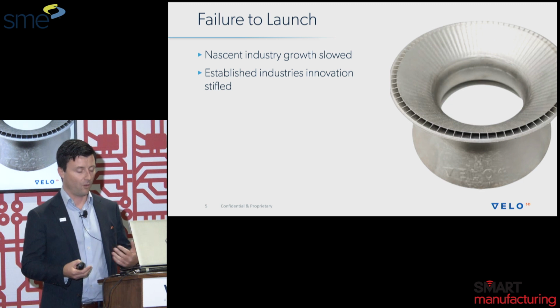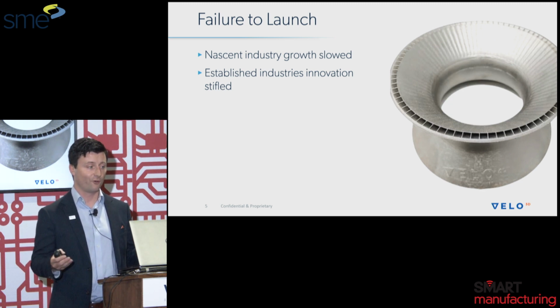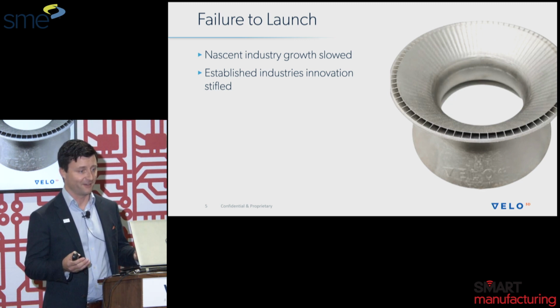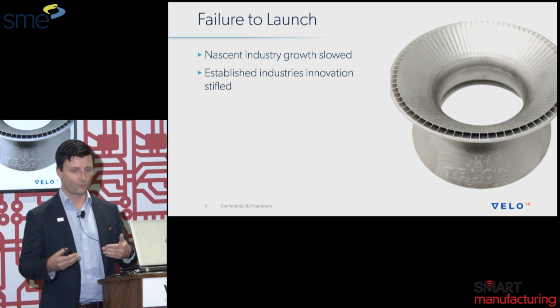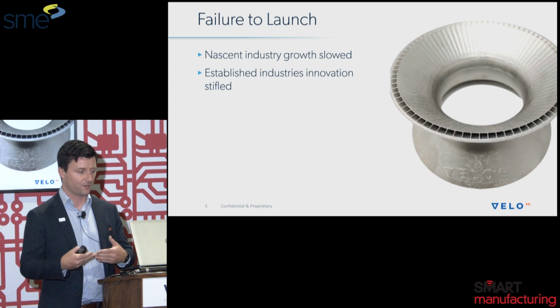One customer that I was talking to is a really great example of this. They bought a big format system with 4 lasers because the goal was, I'm going to make big parts and I'm going to make them fast and we're going to get these things to space. The problem they ran into is that when you're printing these very thin walls with multiple lasers, where the lasers overlap, if your overlay region is not dead on, you start to get holes in the walls of the parts.